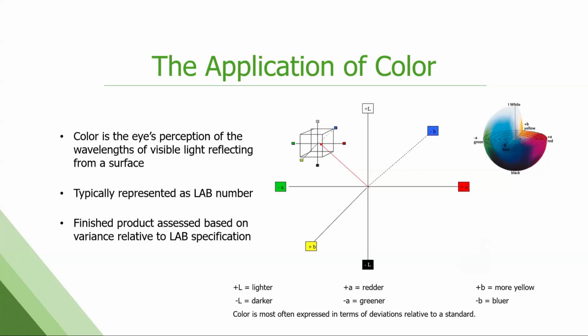We measure an LAB value, that's light, dark, you know, green, blue, red. Every single time we go up on an order, we are controlling that color to a, quote, master standard that's stored in the computer and making sure that the deviation is very small. The human eye doesn't start to pick up color difference until you approach what we call a delta E, or a color shift of 1 unit. We are controlling to 0.5 or less in production most of the time. So the untrained eye, even the trained eye, is going to have a very difficult time seeing a difference in color.